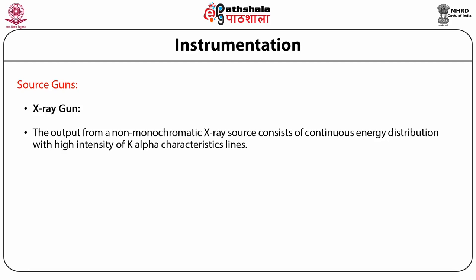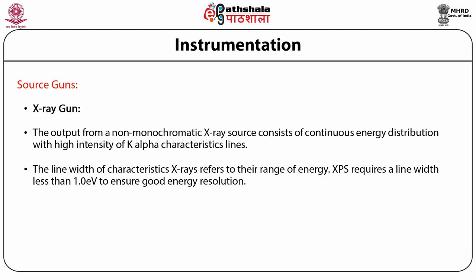The reason to choose lower energy X-rays is their narrow line width. The line width of characteristic X-rays refers to their range of energy. XPS requires a line width less than 1.0 electron volt to ensure good energy resolution. Both aluminium K alpha and magnesium K alpha exhibit line widths less than 1.0 electron volt and also have sufficient energies for photoelectron excitations. Now, the electron gun.